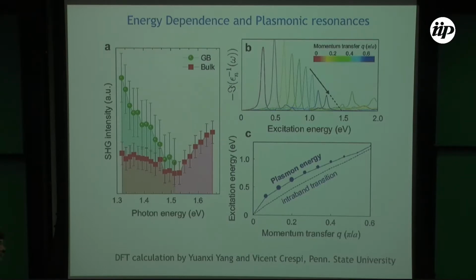The grain boundaries are metallic. That was the idea behind it. Because we observe this enhancement just below the band gap, we started to think that this was coming from these metallic states on the grain boundary. So in fact the grain boundary is acting like a nano antenna. It's enhancing the second harmonic signal that's being generated.